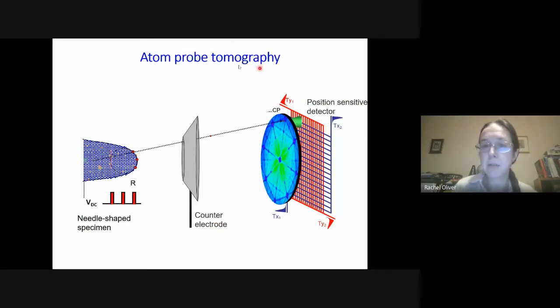Well, they might use a technique called atom probe tomography. What we've got here is a needle-shaped sample where the apex of the needle is about 100 nanometers or so. And it's held at a very high voltage. And it's also at a low temperature. And we just use a little pulse of additional voltage superimposed on that high standing voltage. And that will take the material over the threshold for field evaporation. And because of the presence of the counter electrode,